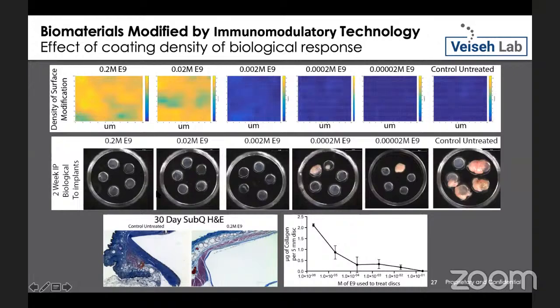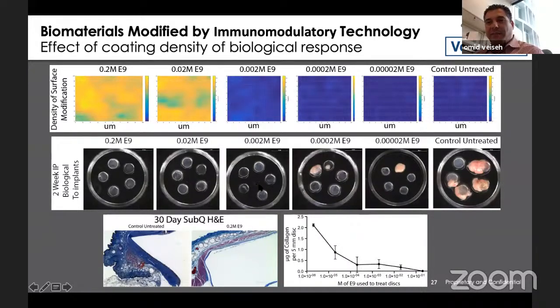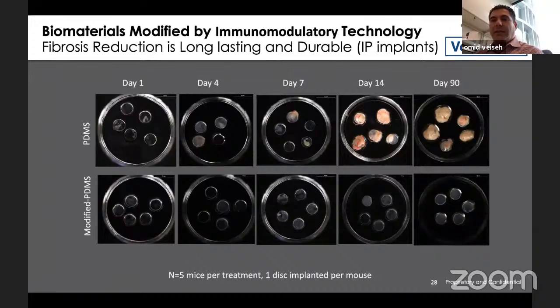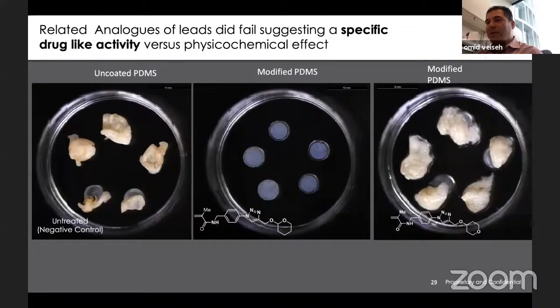So basically, the conclusion of this slide was that our small molecules have drug-like activity in that you see a dose-response correlation between the amount of small molecule present and the foreign body response outcomes. And our results are actually durable in that the small molecule, when it's applied, has long-lasting effects. In this study, we went out for 90 days, and you can see that each of these discs went into a different animal. And with the modification, you're actually able to address this foreign body response.